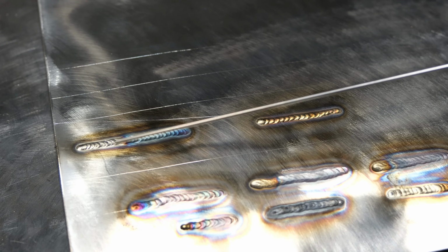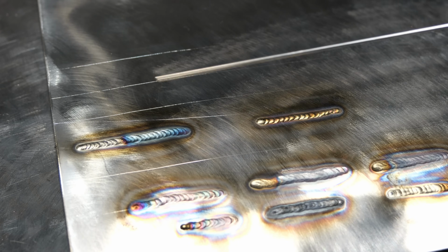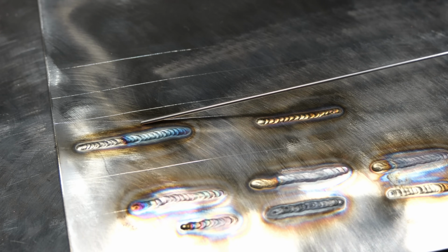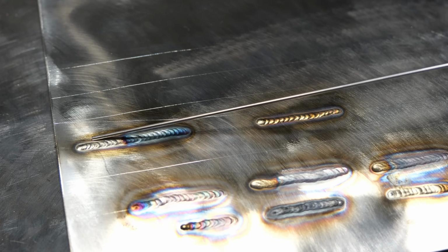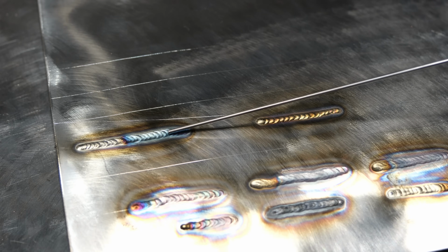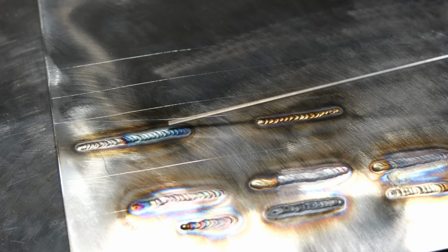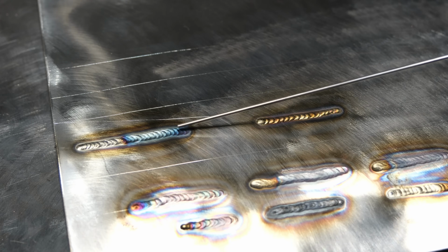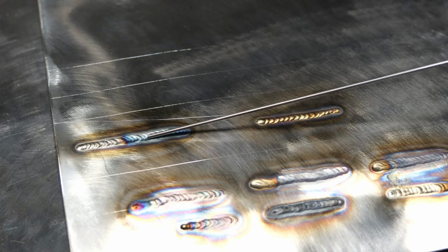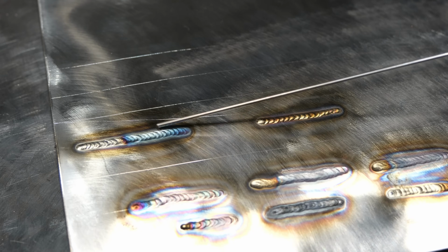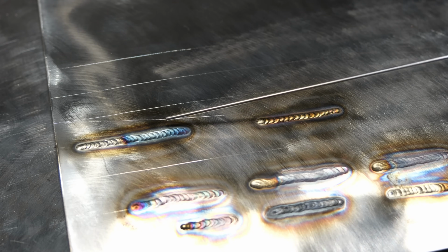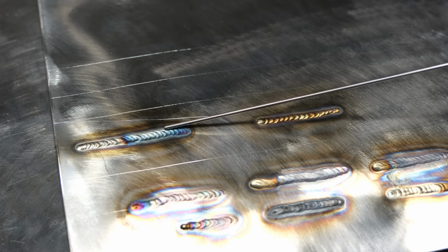This is about what you would want to see on this thin a material. There is some reinforcement up over, especially here, and it's not sunk in. You don't have that dreaded line that's telling you you have a thin spot. The overall weld looks really good. The blue color will clean right off with a brush, and you should maintain most of your corrosion resistance with this weld. So overall, this is very acceptable.